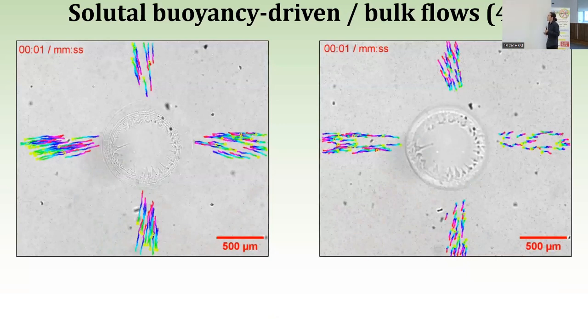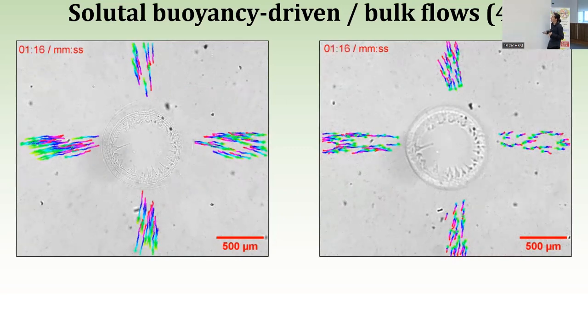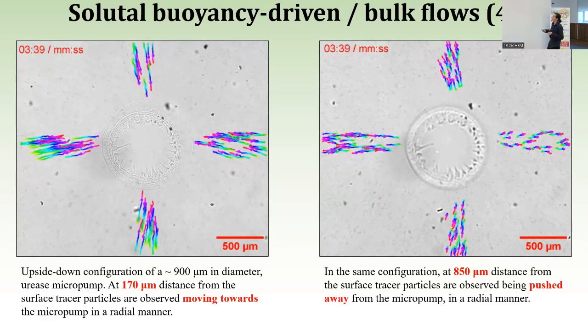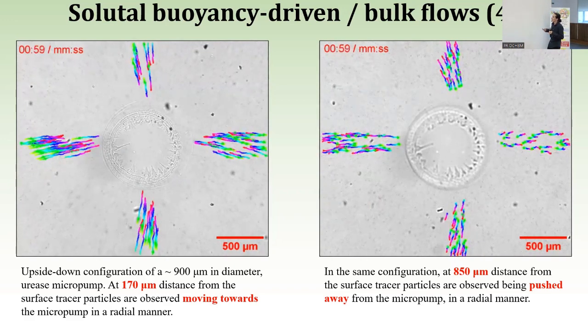To further add proof to this theory, that these flows are generated due to the concentration gradients of the product and the substrate, we conducted experiments in which the parameters were the same, except we turned the whole setup upside down. So the micropump this time was up above. And so this is what we obtained. As we expected, the flows reversed.